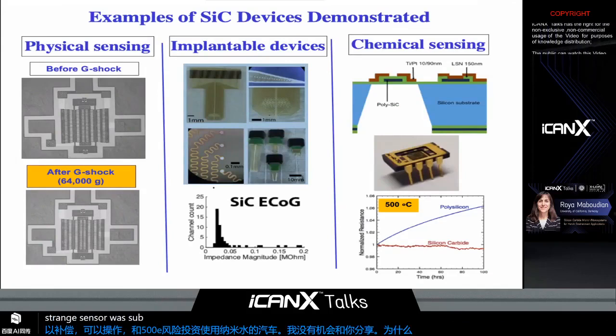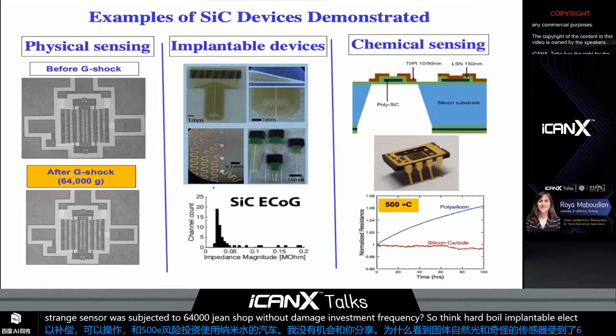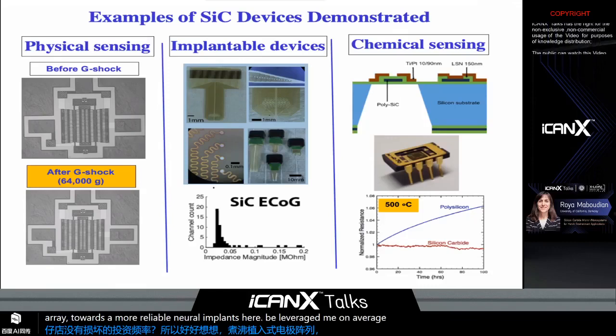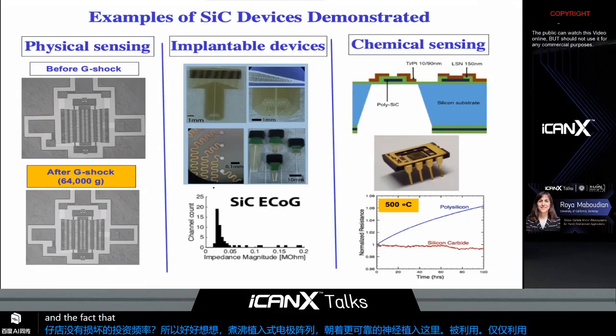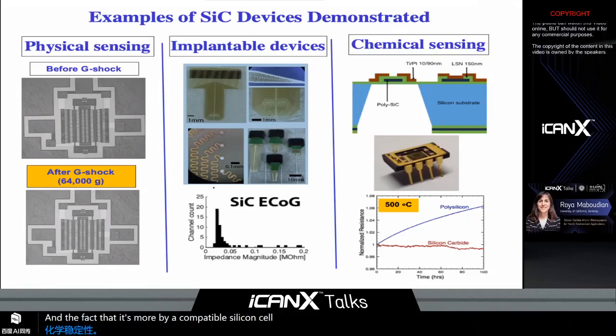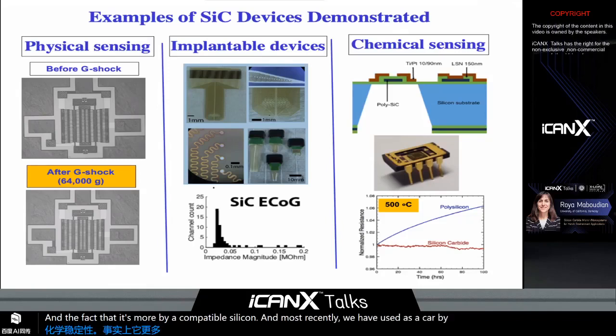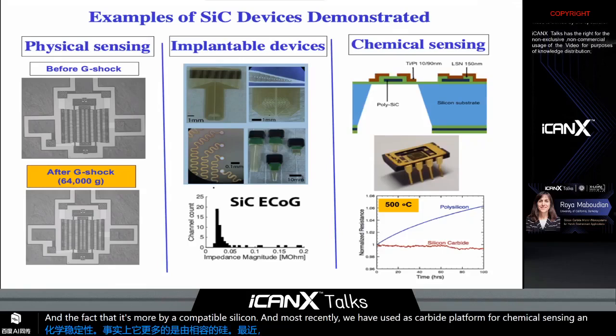And strain sensor that was subjected to 64,000 G shock without damage or shift in resonant frequency. Silicon carbide implantable electrode array towards more reliable neural implants. Here we are leveraging silicon carbide's chemical stability in bodily fluid and the fact that it's more biocompatible than silicon. And most recently, we have used a silicon carbide platform for chemical sensing under harsh environment.